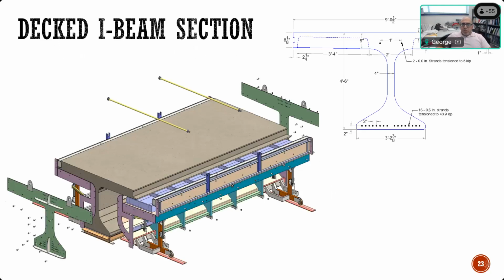So this is one of the early versions of that system, and it was modified a few times until we have the final version that will be produced this summer by Gage Brothers in South Dakota. As you can see here, it's very similar to an I-girder, but with a full width top flange, pretty much 10 feet or whatever the spacing is. And the nice thing is that the deck slab is not a solid slab. It has what's called a ribbed slab. So it has a very thin skin, about 2.5 inches average thickness, and it has openings between those.